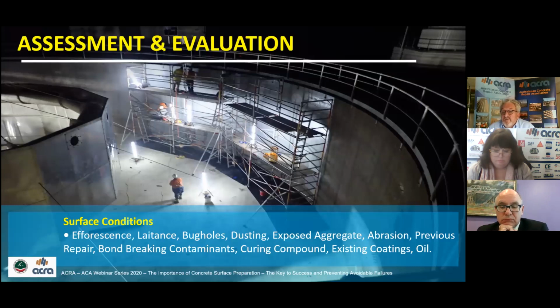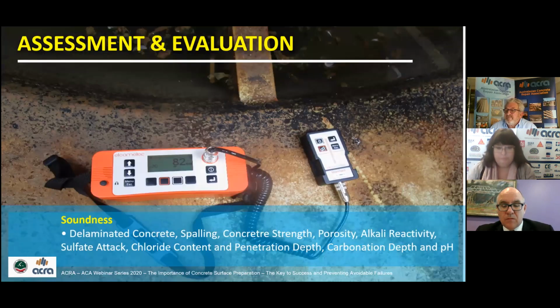The surface conditions are important. Efflorescence, surface imperfection, laitance, bug holes, dusting, exposed aggregate, abrasion or cavitation damage, previous repairs that may not be sound, any contamination that will possibly not be receptive to the bond of material going over the top, curing compounds, existing coatings, and oil. Soundness, the soundness of the concrete, delaminated concrete, spalling concrete, surface strength, the porosity of the concrete, alkali reactivity, sulfate, chloride content and penetration depth, carbonation depth, and pH of the concrete are all important considerations.